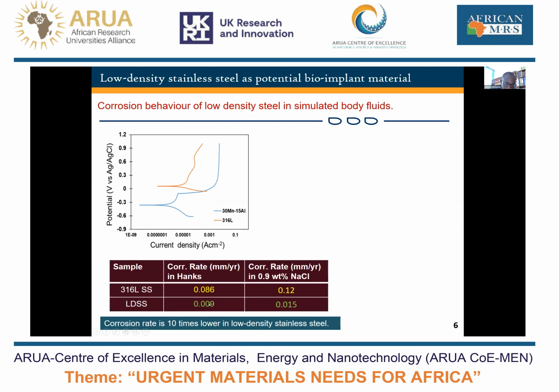Now you see that the low density stainless steel grades have a corrosion rate that is 10 times lower than that of 316L stainless steel, and this is just in the as cast form, both in Hanks solution and of course in 0.9 wt% NaCl. These two solutions are considered simulated body fluids basically. So that was quite interesting.